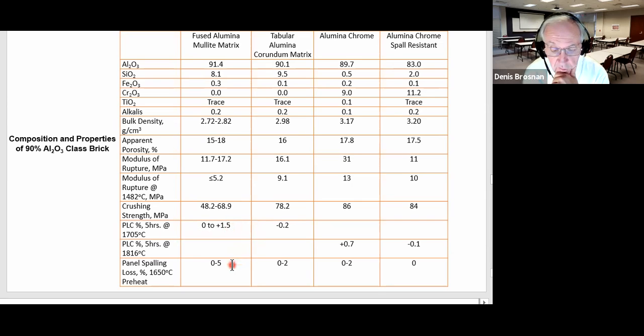Another difference is in this so-called panel spalling loss. The panel spalling test is a refractory test where a panel of bricks is preheated, and then the panel is opened up with an air blast in it. There's a certain number of cycles for that, and the percent of material that spalled off or cracked off and fell off during that test is a lot different.